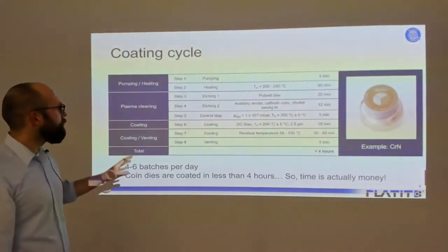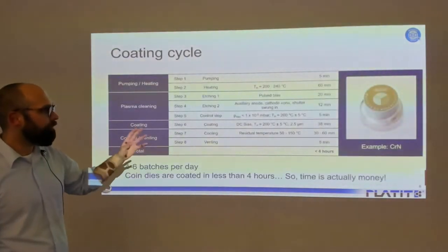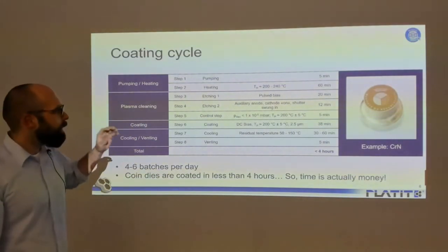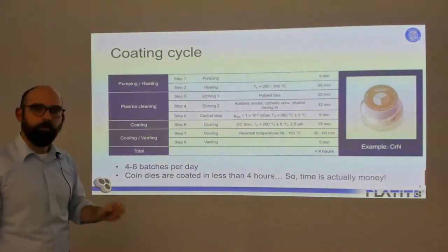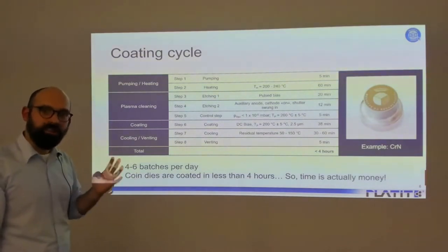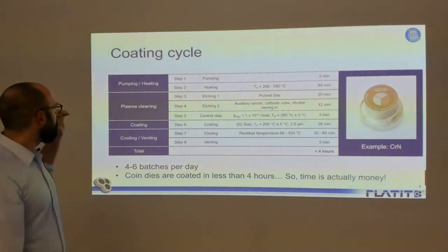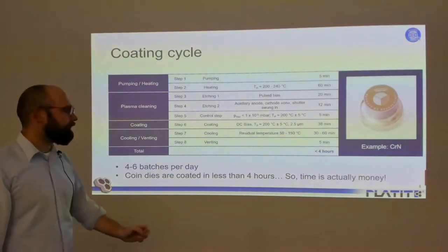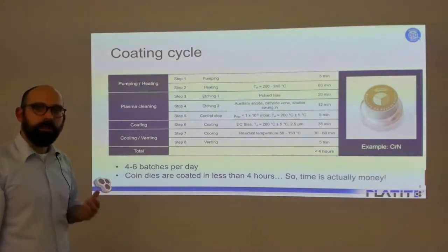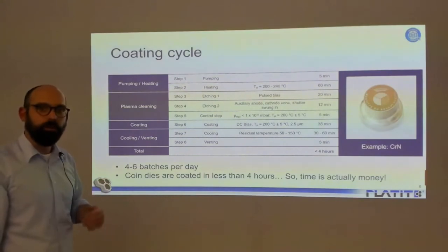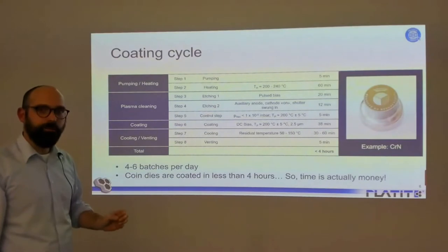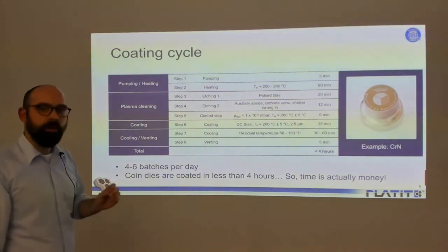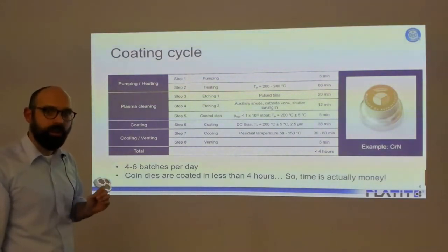And how one of the recipes works, I'm going to show you by the example of chromium nitride. I'm not going through the details of every recipe step. I'm going to break it down for you into four simple basic steps. Step number one is pumping and heating. The chamber is evacuated and heated up to a temperature of approximately 200 to 240 degrees Celsius. This temperature is feasible for the majority of steel grades that are used for coin stamps. However, if you use different steels or have different temperature requirements, talk to us. We can take care of that.